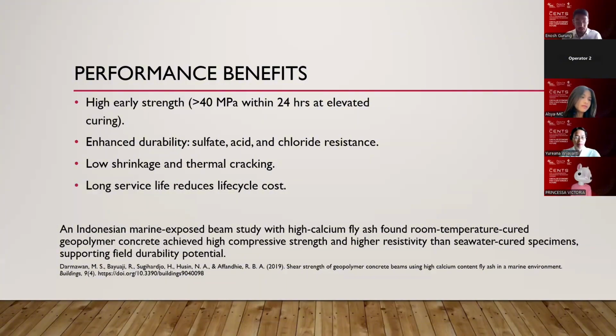Geopolymer concrete shows better resistance to chloride, acid, and sulfate than OPC. Shrinkage is lower, permeability is lower, and service life is longer. An Indonesian marine-exposed beam studied with high-calcium fly ash found that room-temperature-cured geopolymer concrete achieved higher compressive strength and higher resistivity than seawater-cured specimens, supporting field durability potential.